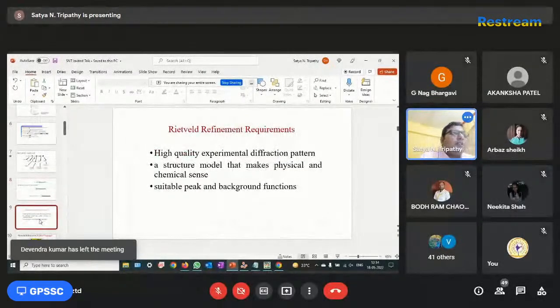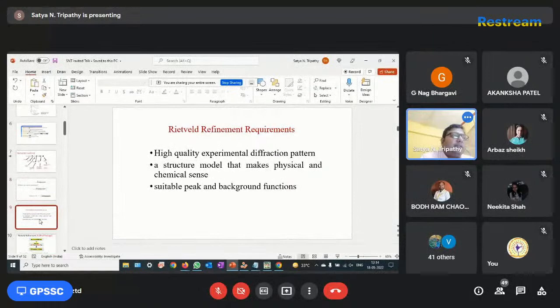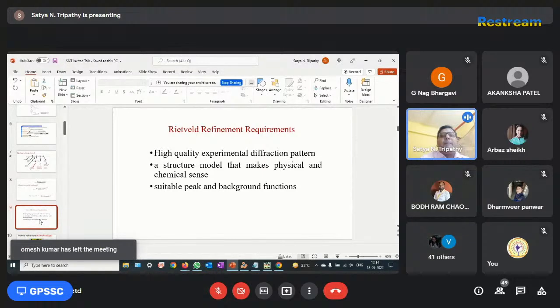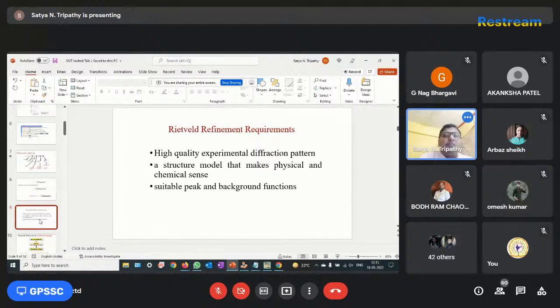To do the Rietveld refinement, the first requirement is a high quality experimental diffraction pattern. This is the most important part. For this purpose, you should take the data with a very slow scan, so the time has to be very large for each small reading, 3 degrees per minute or 4 degrees per minute. The distance between two data points is like 0.01 or 0.005. It's up to your choice.